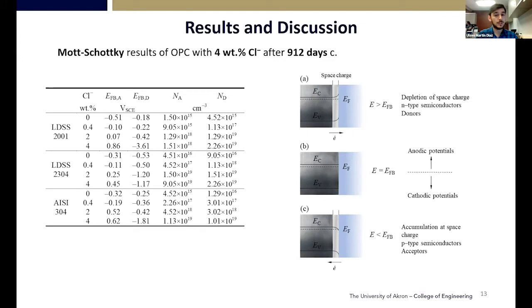A similar trend could be seen with all 3 stainless steels, where the flat band of the acceptor increased toward higher potential as time went on, which shows that this higher potential meant that the chromium oxide was able to accept more electrons easier, meaning that as the passive film was growing, so was the corrosion protection. However, the flat band for the donor part was becoming more and more negative, meaning that the iron was also able to donate these electrons, becoming a more porous and more doped passive film.